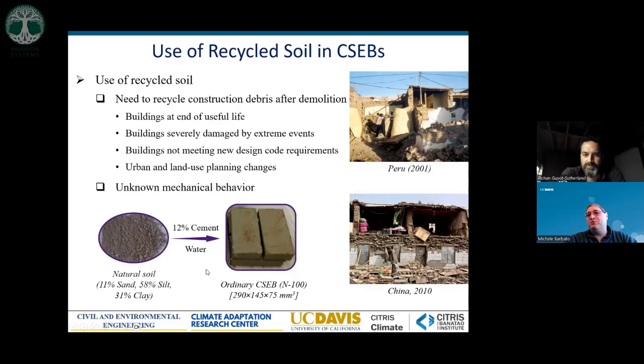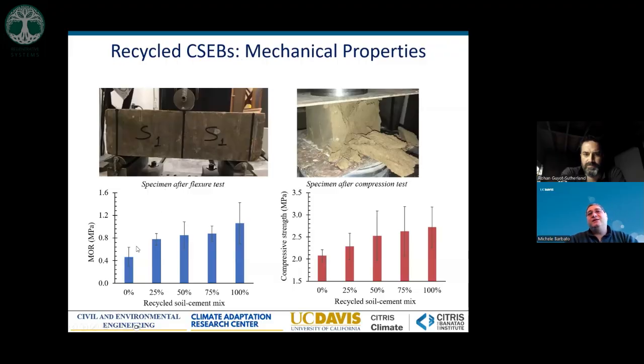We made our blocks, which we investigated in the same way we did with the other ones. And then after breaking them, we used the material from the broken soil to fundamentally recycle it by grinding it and then remixing it with a different amount of natural soil and cement to produce new bricks. And the comparison was done in terms of flexural strength and compressive strength.